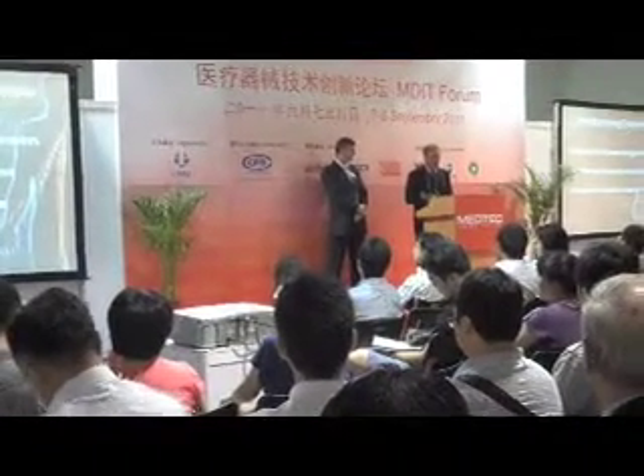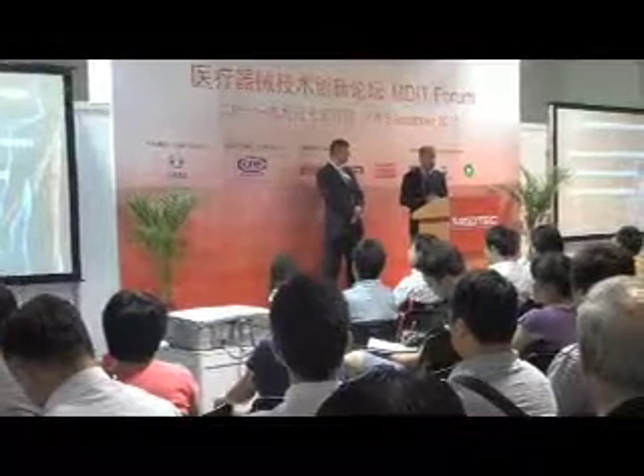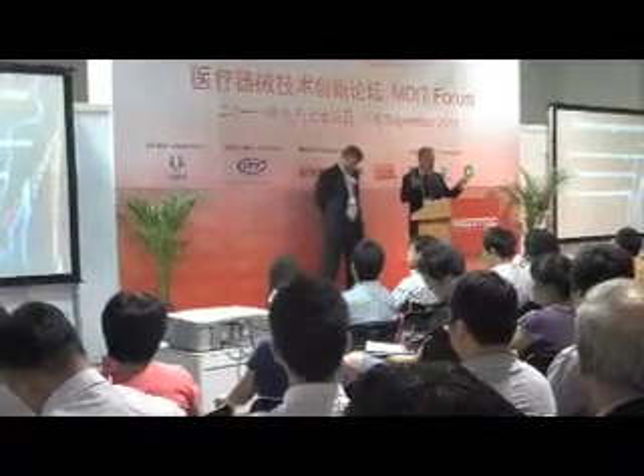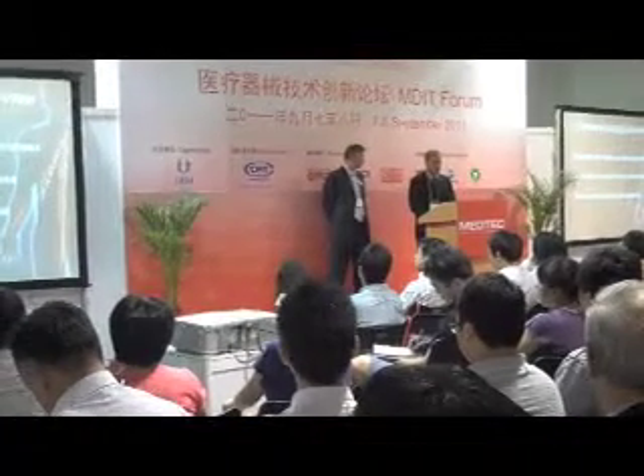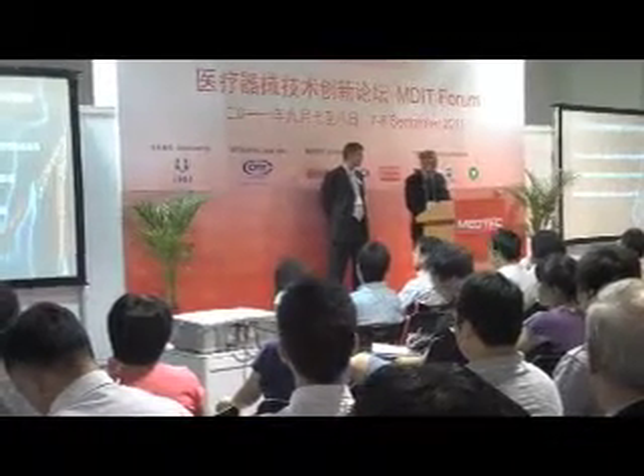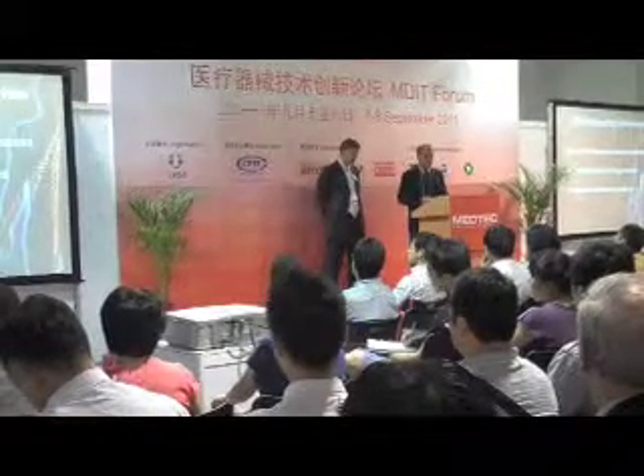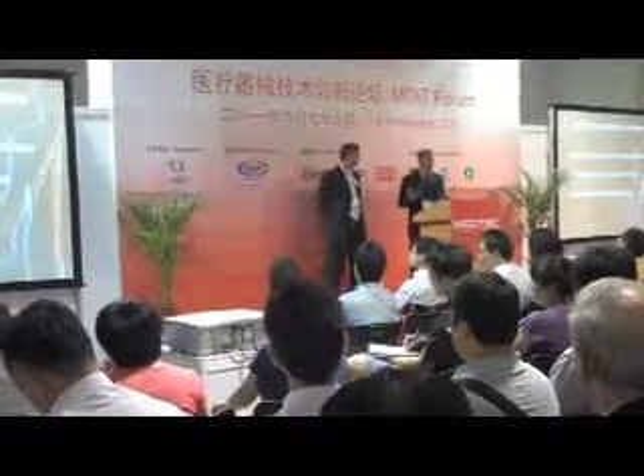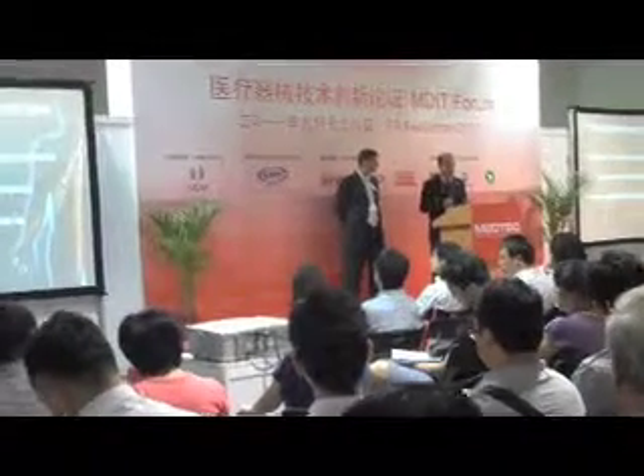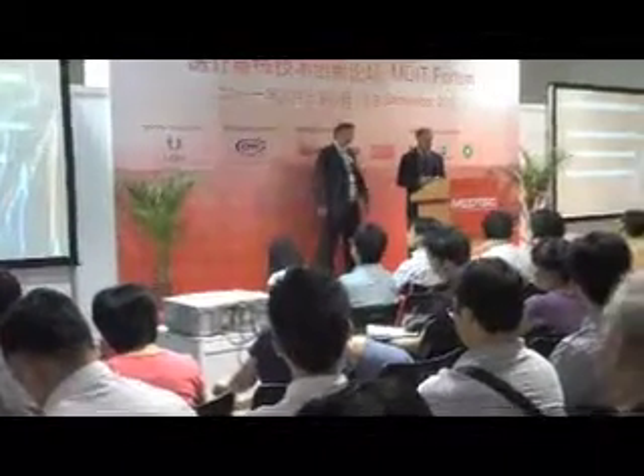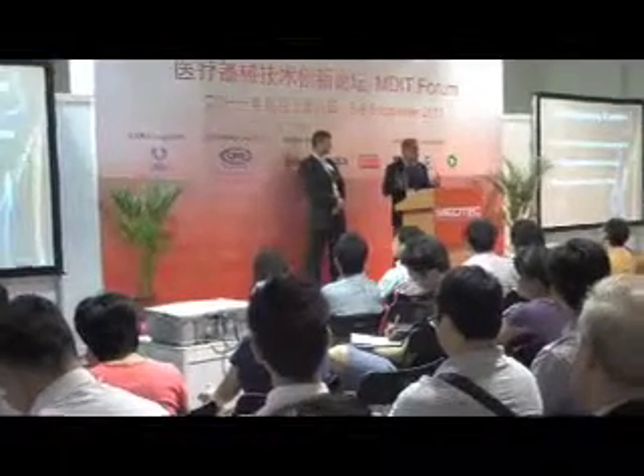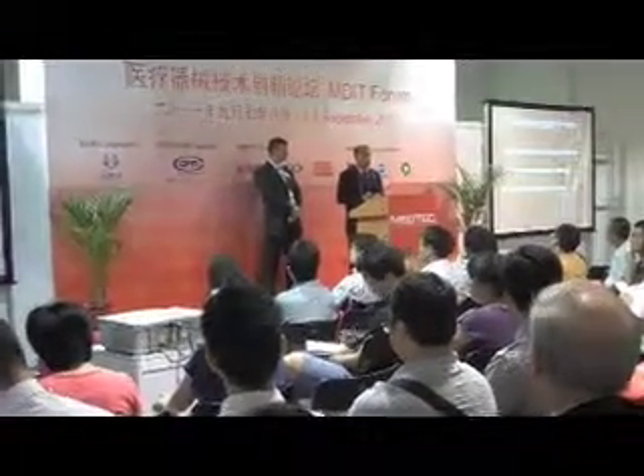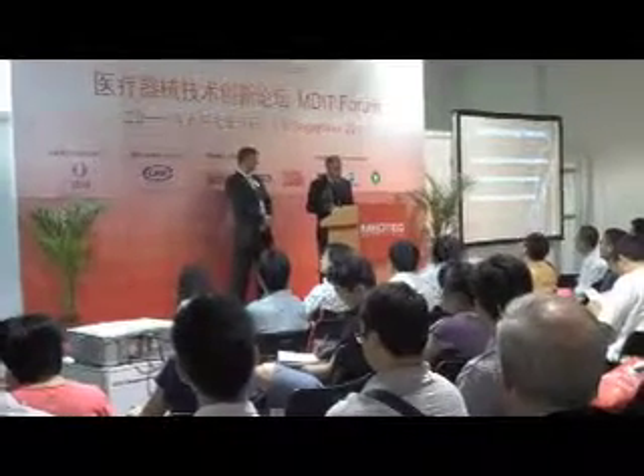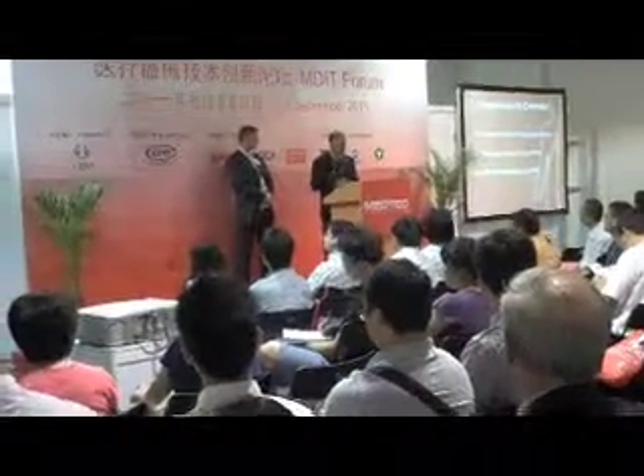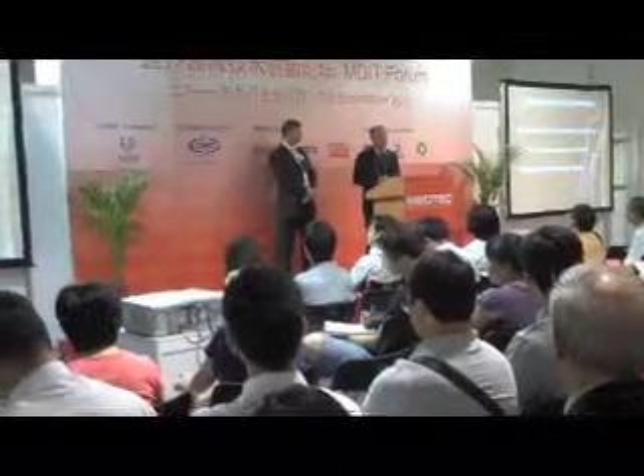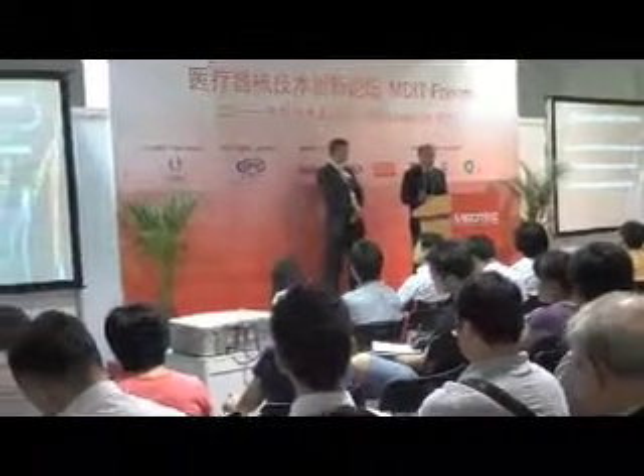We also then optimize the mixing process. This is discussed before. This is primarily determining time and temperature in order to completely cure the drug and silicone mixture. And then finally, it's important that working with our clients we develop lot acceptance characteristics, lot acceptance requirements. This can involve visual standards for the finished part. It can also involve mechanical properties, but probably most importantly is the drug elution characteristics. And that is typically measured using equipment such as high-pressure liquid chromatography.